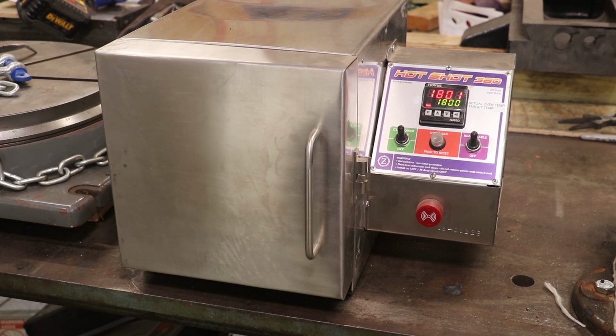So the final stage after we do the heat treat here, this hardening is going to make it very hard but also very brittle. We want to actually temper it back so that it's not as brittle. And to do that, we run it through another temperature but not nearly as hot. According to the book, it's 300 degrees is where we need to go to, and hold it there for about an hour, and then let it just cool down, and we should be good. So anyway, waiting on our alarm. Should be any minute now.